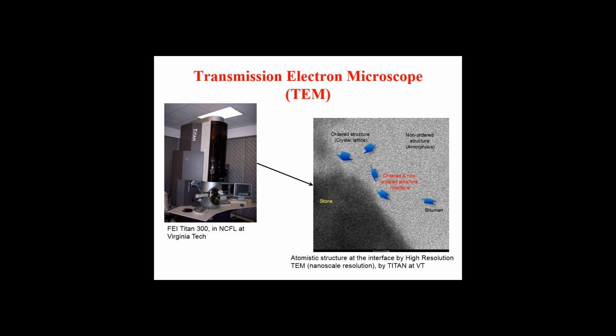And this is a transmission electron microscope. With this project, we actually identified some kind of interface between asphalt binder and aggregates. On this screen, you will be able to see some kind of grains in the aggregate, but here it is amorphous. This crystal structure can be seen from the TEM. And you will see some smear region between this crystal structure and the amorphous material. That means there's some kind of boundary interface between the asphalt binder and aggregates, and that's roughly 5 nanometers. That's what we measured from this project.